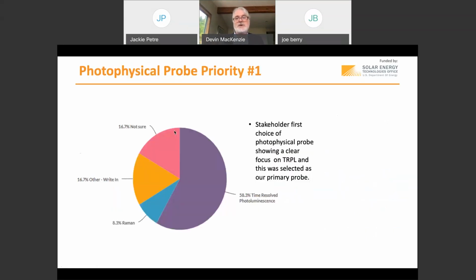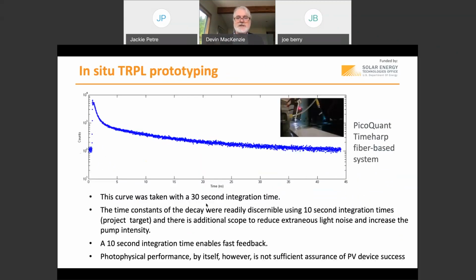But we took a stakeholder poll. What's the stakeholder choice for the first choice of photophysical probe? Again, the goal of this project was to develop in situ photophysical monitors to monitor growth of perovskites and feed back in an in situ, continuous way. There was general strong agreement that time-resolved photoluminescence was broadly accepted as quite useful. It's the simplest but most direct way of measuring the optoelectronic quality of the film. And this is an example we built.